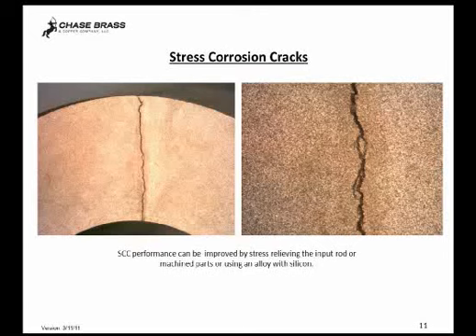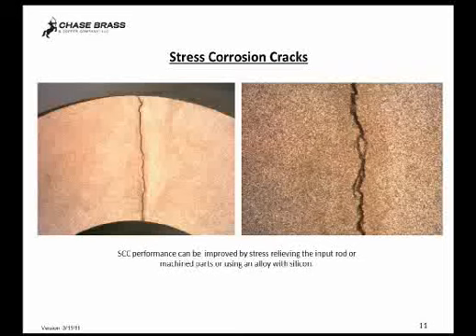Stress corrosion cracking performance can also be improved if you stress relieve either the input material, the input rod or forging, or if you stress relieve the machined parts to take the stresses out of the whole manufacturing operation, or by using, as we can show, alloys that contain silicon, which is a known stress corrosion cracking improvement addition.